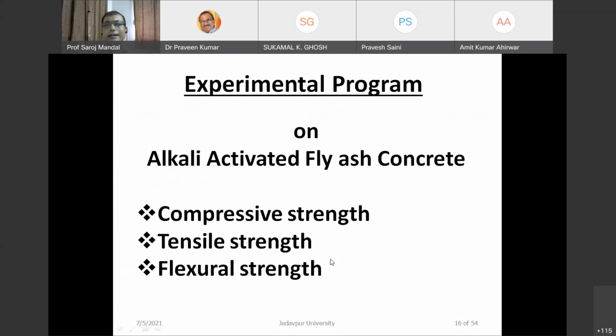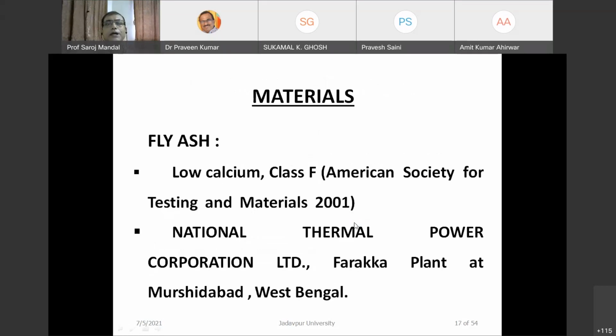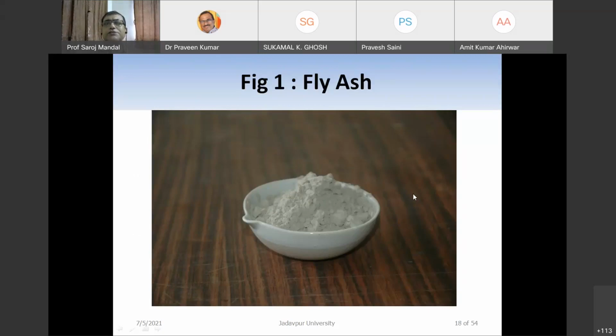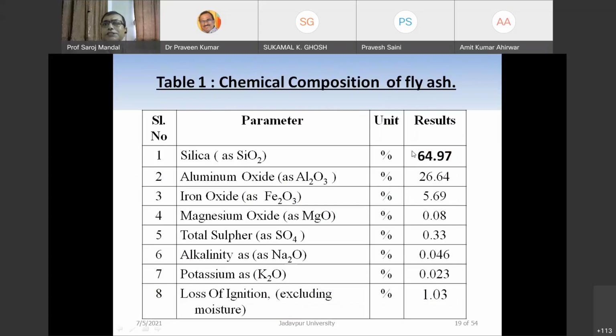So now let us come to alkali activated fly ash concrete. First we are restricted to compressive strength, tensile strength and flexural strength. If we come to the fly ash, the source of these materials is low calcium class F, as per the American ASTM, American Society for Testing and Materials. Class F means it has no binding property itself. There is another type, class C, which has its own binding capacity. But for class F, there is no binding capacity itself. And this is collected from the NTPC Farakka plant. This is very fine material. This is what is called fly ash. It is very fine and white in color. Silica content, if you see, is about 64.97.